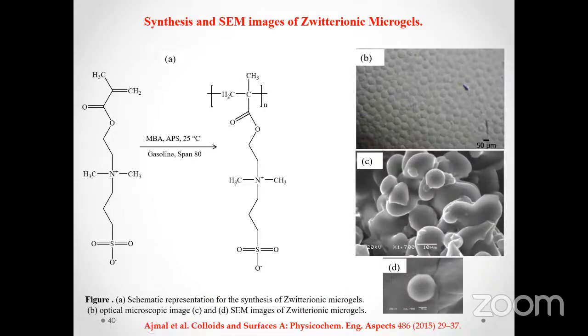This is another hydrogel system. In this case, we have prepared a zwitterionic hydrogel, which contains both positive and negative charges in its structure. And again, we have prepared a micron-sized hydrogel system, as can be seen from this first figure, that almost all the particles were having a size around 50 micrometer, and they are all in the same shape. So this is very important, that if you can prepare the hydrogels with the same morphology, then you can get good results in their applications.